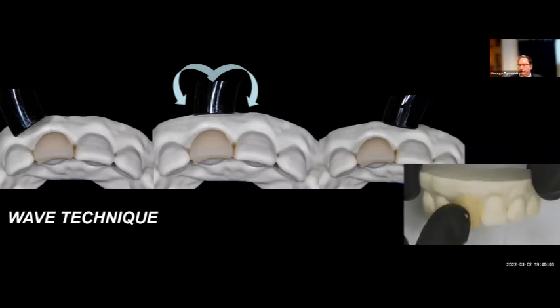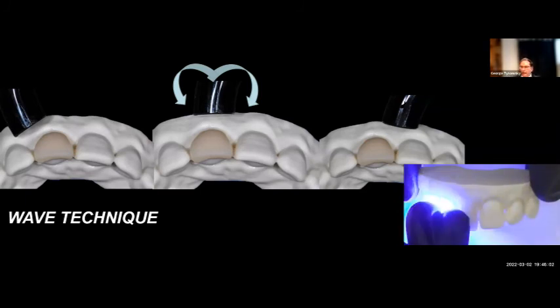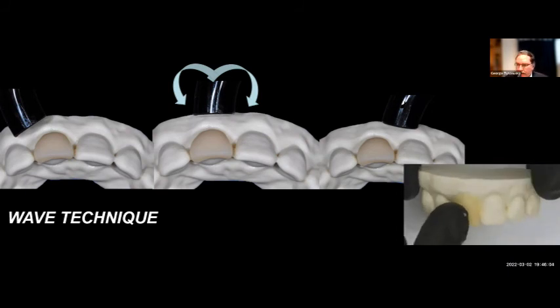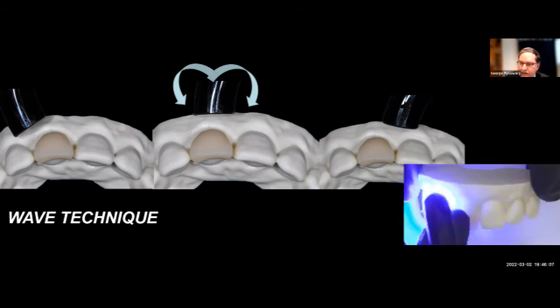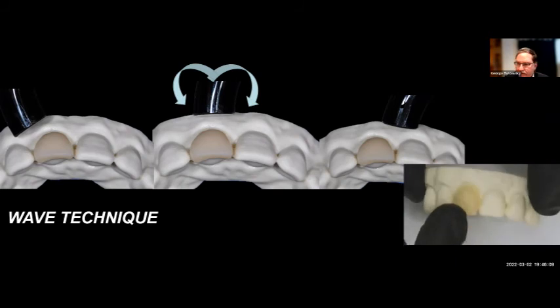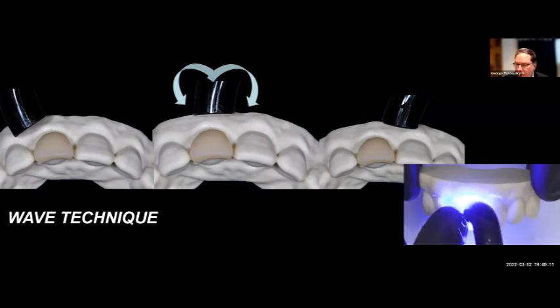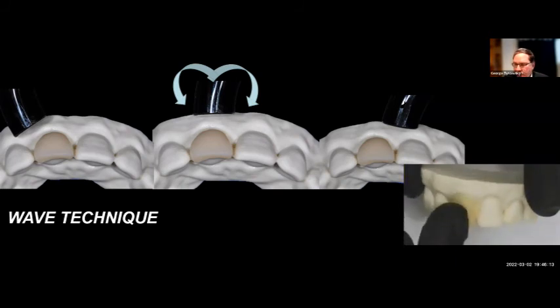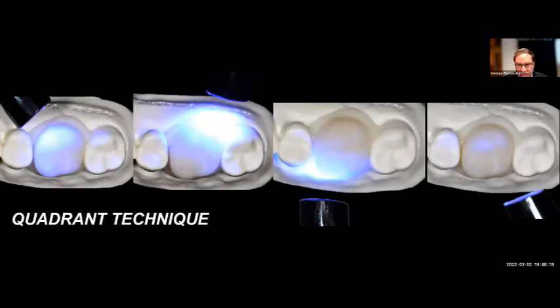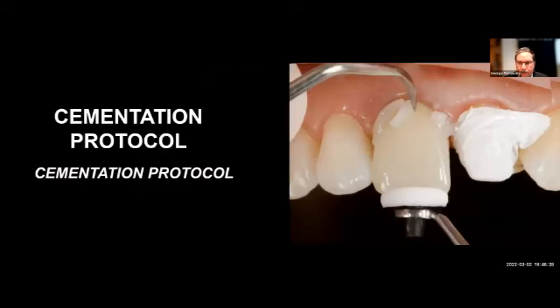We basically take a high strength curing light, wave it, gel it up, and we put it in the gel phase so we can basically peel off the excess cement and keep a clean margin, and then make sure that we don't have any residual in the interproximal areas, and clean up the restoration, then go for final polymerization. So just showing the quadrant technique also from both areas. You're waving the technique and basically gelling it up, peeling it off, and then final polymerization accordingly.